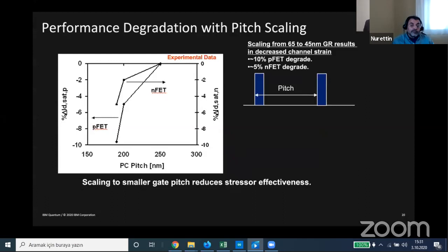When we wanted to go from 65 to 45 nanometer due to the ground rule scaling, the experimental data showed reduced performance as we scaled the pitch of the gates. And the amount of reduction was significant, 10% on PFET, 5% on NFET. Basically, physically, what happens is the stressor effectiveness is reduced as this gate pitch goes down due to the smaller spacing. Less volume of stress material can be put in there. And so we had to overcome this pitch scaling issue with strain.